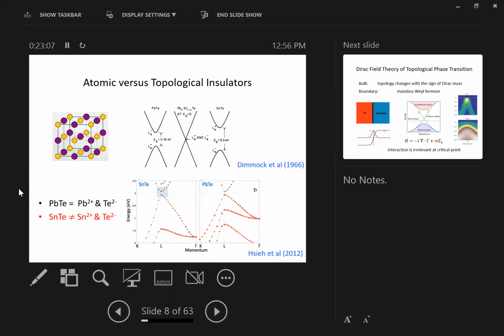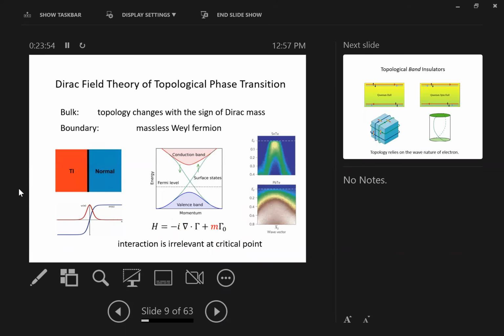This is what you expect from essentially an ionic insulator consisting of lead 2+ and tellurium 2-. Basically, the electrons transfer into the tellurium atoms. In tin telluride, on the other hand, in most part of the momentum space, the occupied states come from tellurium, but just near the valence band edge, the occupied states actually come from atom tin, and the unoccupied states actually come from tellurium. So from this, we know that tin telluride is qualitatively different, is topologically different from an atomic insulator. It's not equivalent to the atomic insulating limit. So tin telluride is a topological insulator.